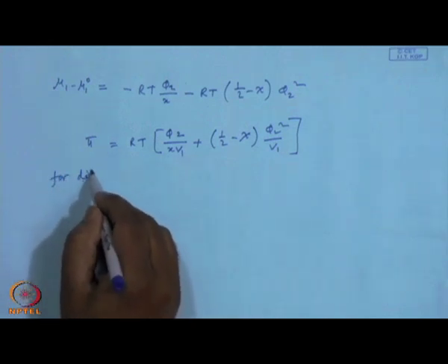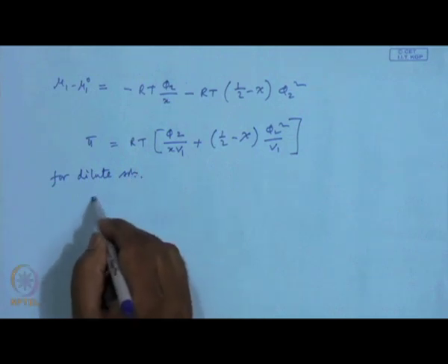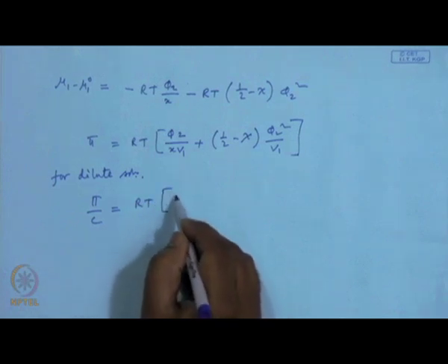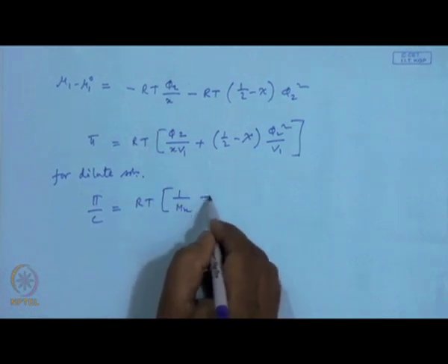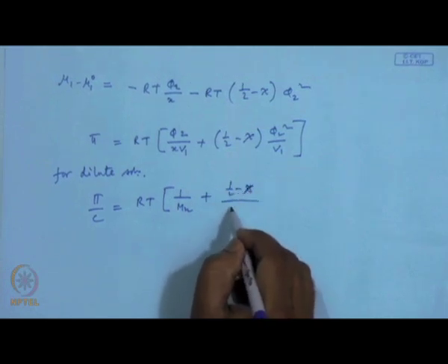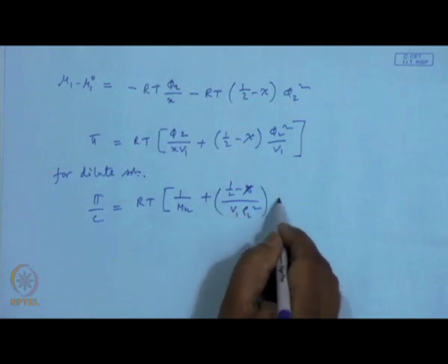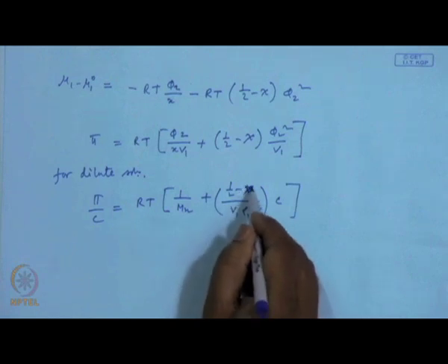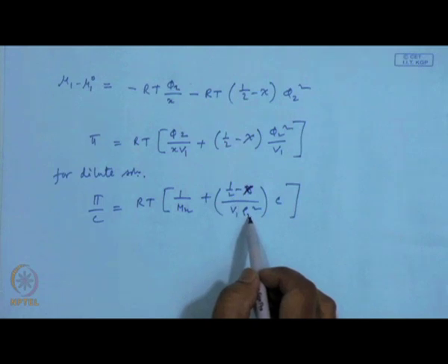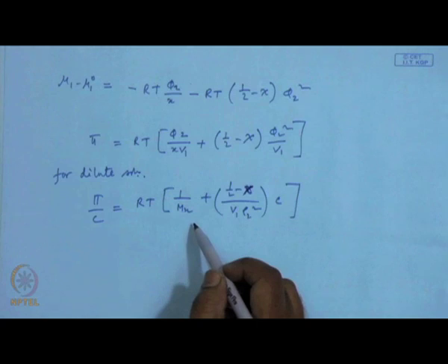So, for dilute solution it can be mathematically shown that we can write the above expression like this, where chi, as you know, is the solvent solute interaction parameter, rho 2 is the density of the polymer molecule, Mn is the number average molecular weight.